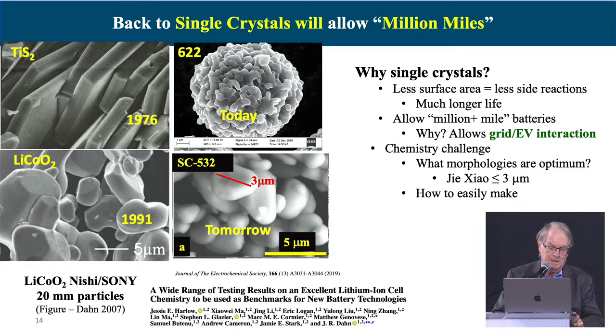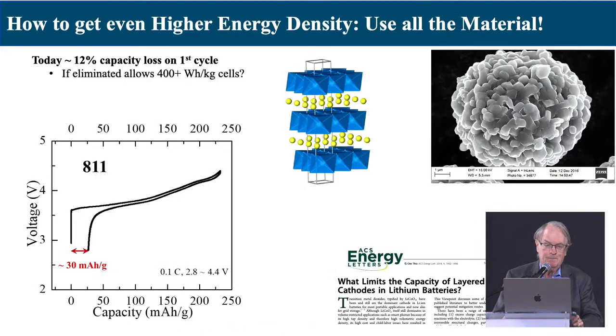So what about this first cycle loss? This is a typical cycling curve. So if you charge it from, say, 3 volts to begin with, up to about 4.4 volts, we tend not to go any higher because of reactivity with the electrolyte. Then you discharge back down again. And I've shown you here a case where we've lost 30 milliamp hours per gram out of the 240 on that very first discharge, and you never get that back. So our goal was to understand why that's occurring and can we solve it.